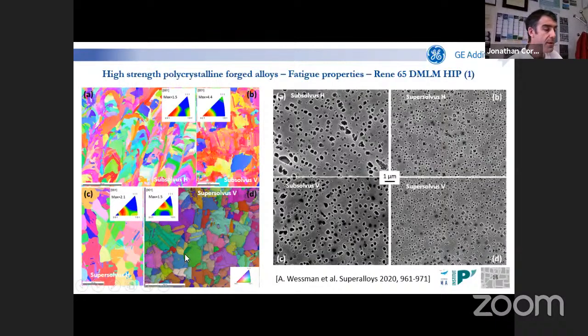material with several twins. And something very interesting is that we are able to reach a grain size which is very difficult to reach with a conventionally processed cast and wrought material, meaning for a cast and wrought material, you have usually 5 to 20 microns grain sizes. And then when you do supersolvus heat treatment, you have grain sizes of typically 200 to 300 microns. So it's very difficult to have an intermediate grain size in which you can optimize both creep and fatigue properties. So we have been able to reach such kind of grain size with this process, thanks to very nanoscale contaminations at grain boundaries, while we have typical PBF-L microstructure in the subsolvus state.